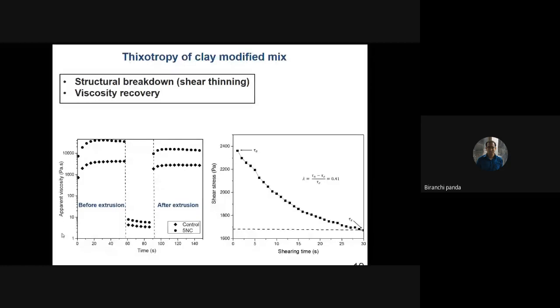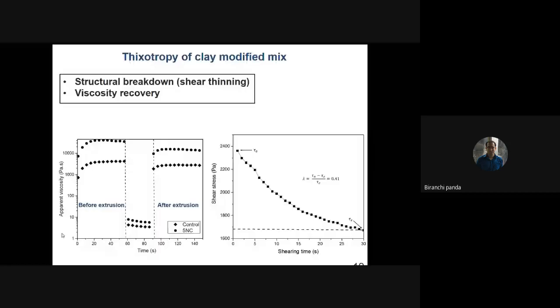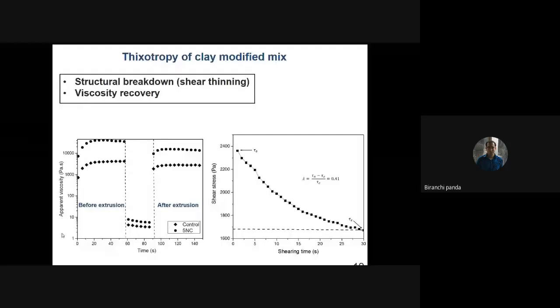Then we can see from this graph that before extrusion, when the material was at resting condition, it has high viscosity, meaning it can stay in a stable position. During extrusion, when you apply a high shear rate, it completely loses its viscosity, and the value, if you see, is below 10 pascal second. So it is a very good material. You have to apply very small pressure to extrude it. But now let us see what happened after the extrusion. After you extrude it on the print bed, the material has the capability to recover its original viscosity. Though it loses its viscosity during extrusion, after extrusion it can recover around 80 to 90% of its original viscosity.